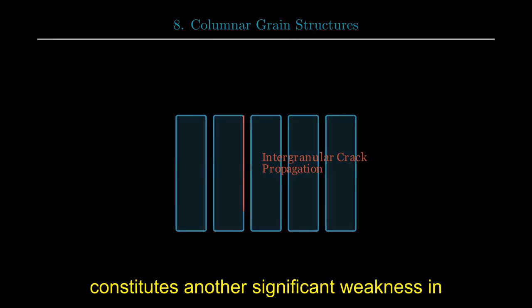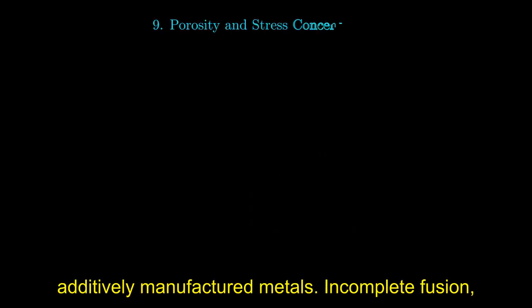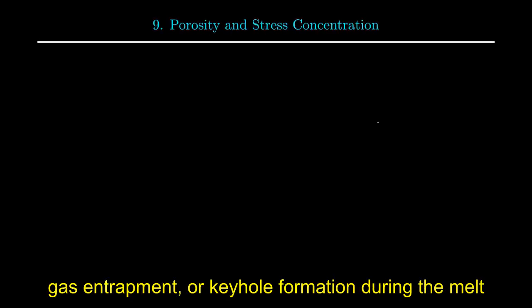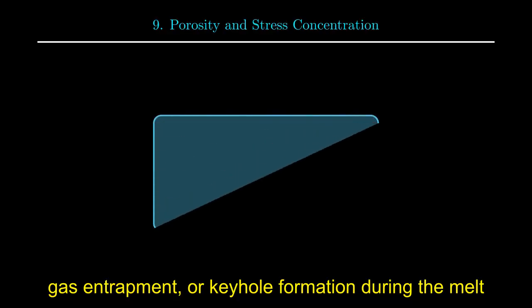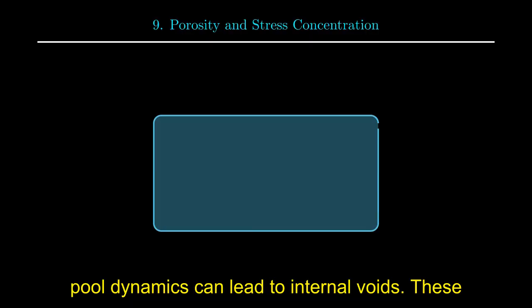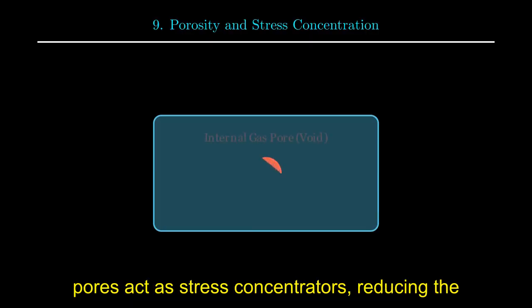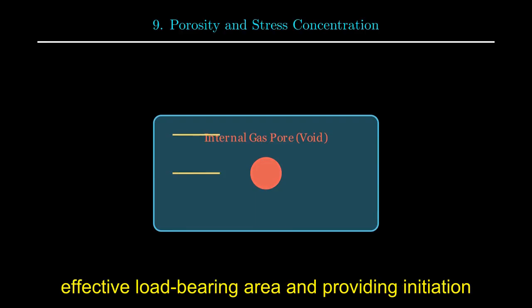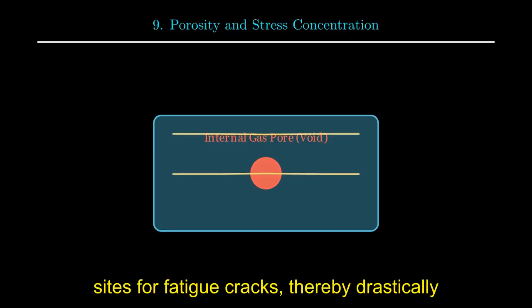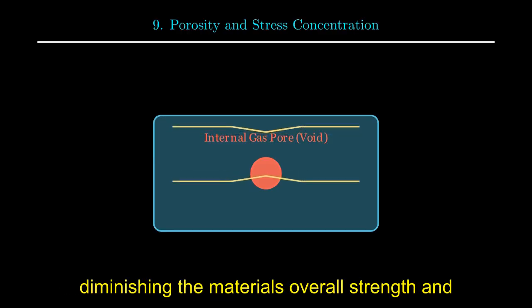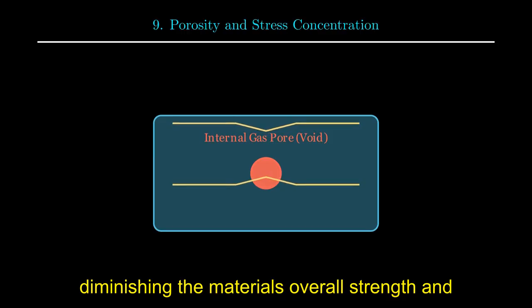Porosity constitutes another significant weakness in additively manufactured metals. Incomplete fusion, gas entrapment, or keyhole formation during the melt pool dynamics can lead to internal voids. These pores act as stress concentrators, reducing the effective load-bearing area and providing initiation sites for fatigue cracks, thereby drastically diminishing the material's overall strength and ductility.